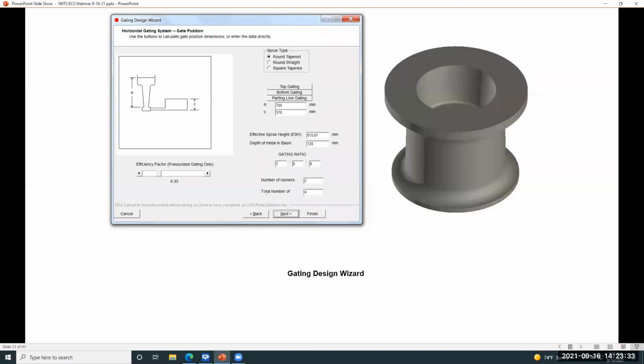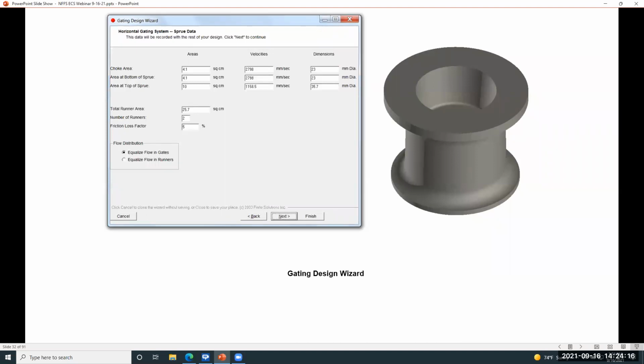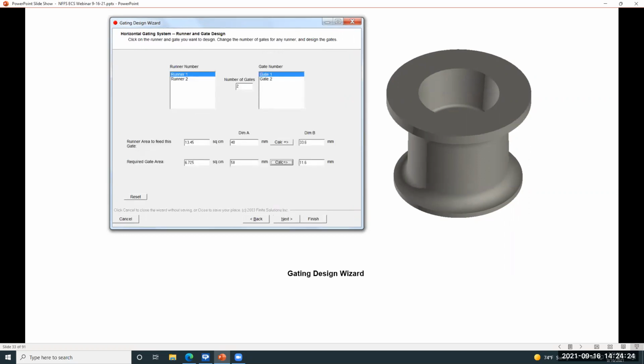This refers to the height of the metal that's falling, and that's what provides the metal velocity within the gating system. We can enter a gating ratio, which is the ratio of the cross-sectional area of the sprue to the runner to the gates. So in this case, we have a 1:6:6 ratio, the sprue being the smallest number. This is what we call an expanding or a non-pressurized system. And then we can set the number of runners and the total number of gates. The system then goes through and calculates all the appropriate dimensions for the sprue, for the runner, and the gates.